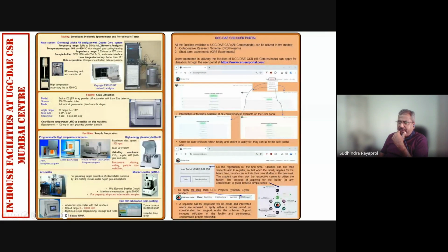We also have a very large broadband dielectric spectrometer, which can be used from low temperature, from liquid nitrogen temperature to room temperature, and with the additional accessory of a high temperature furnace, we can go up to 1200 degrees centigrade. The frequency range which we can measure is from 3 microhertz to 3 gigahertz with a network analyzer, and this is that network analyzer, and this is all automatic systems.